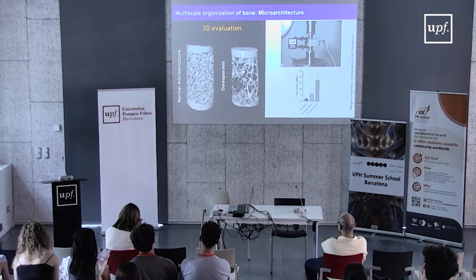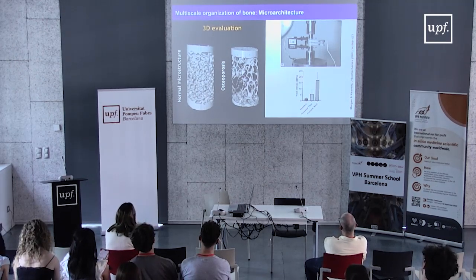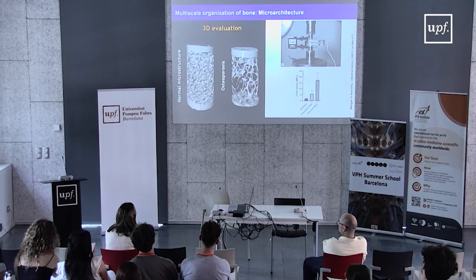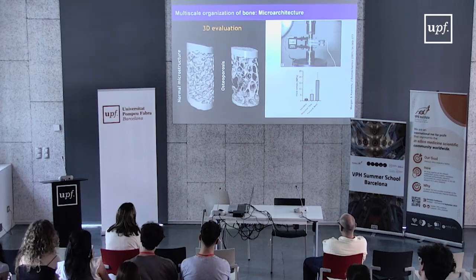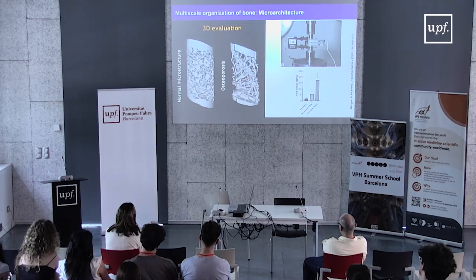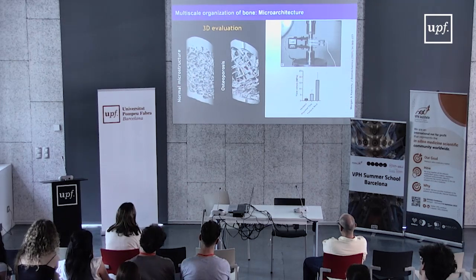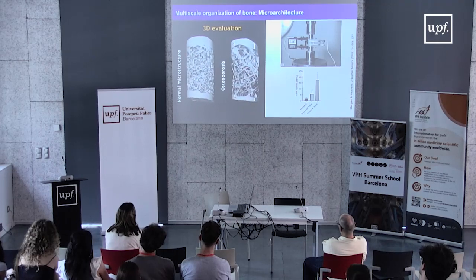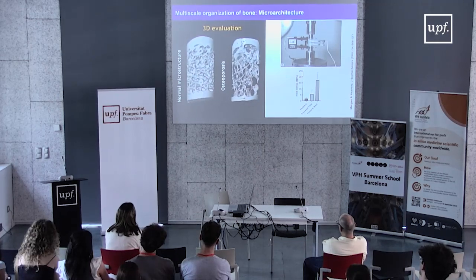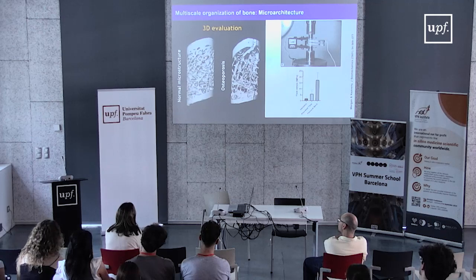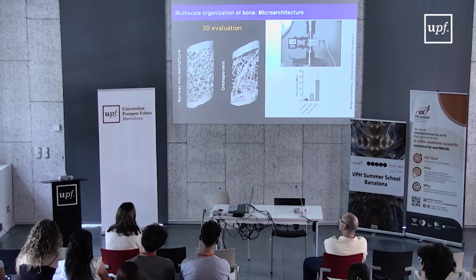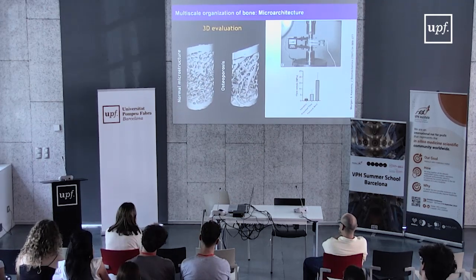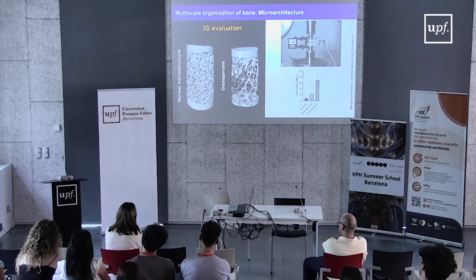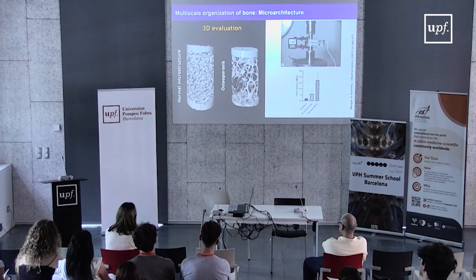This is what we evaluate in clinics when we perform a bone biopsy or when we look at peripheral quantitative CT scan. If we reconstruct the biopsy in 3 dimensions, you can see that in osteoporosis, we don't have the same organization of trabeculae as in a normal bone. And of course, we can apply some mechanical testing, especially compression load, on this type of biopsy core, and we can measure the strength which is required to break the bone.